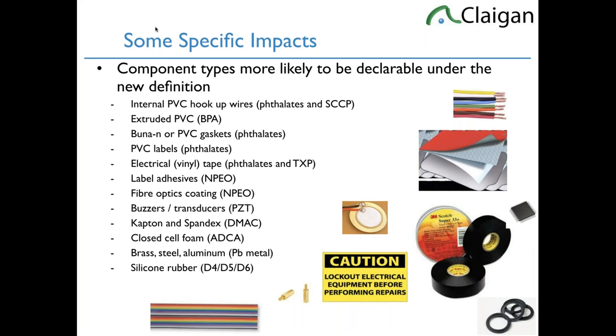It's a significant deal. Bisphenol A: a lot of people focus on polycarbonate, but polycarbonate, which is made from bisphenol A, is usually fully reacted. It's only a trace amount of BPA left over. Where we actually see it in higher concentrations is as an antioxidant to the plasticizers in extruded PVC. It's much higher concentration there. Nitrile rubber and PVC gaskets and soft parts have phthalates, making them bend. PVC labels: most vinyl labels are flexible. Not the polyester ones, they're flexible too, but they're not phthalated. PVC labels often used for safety are very commonly phthalated.